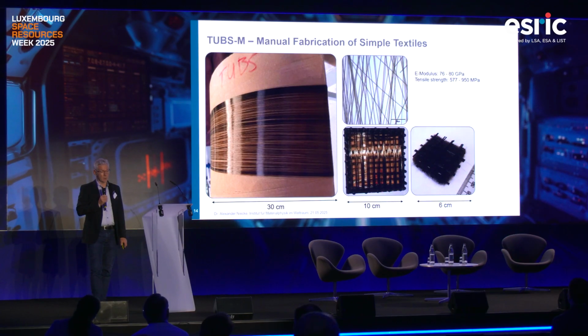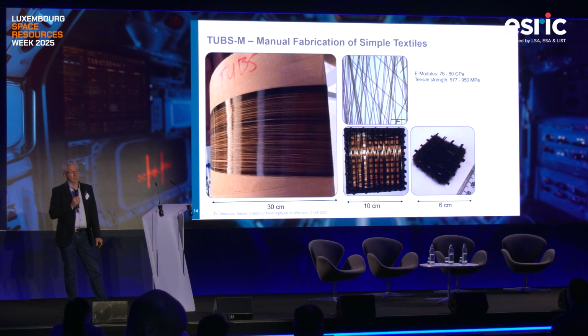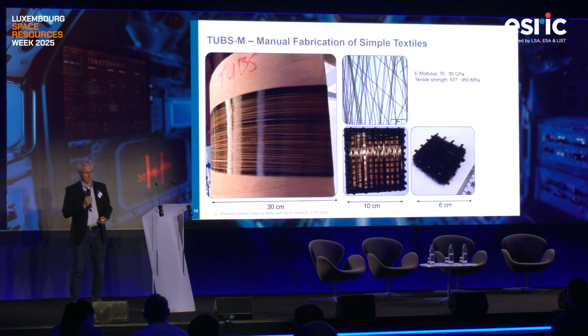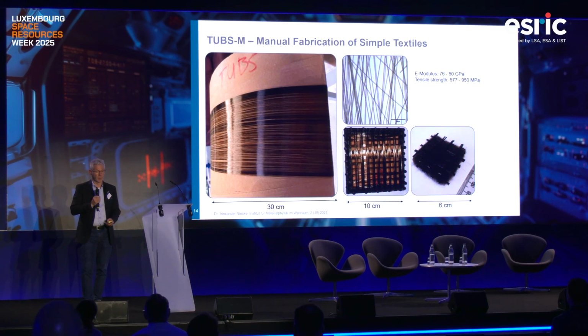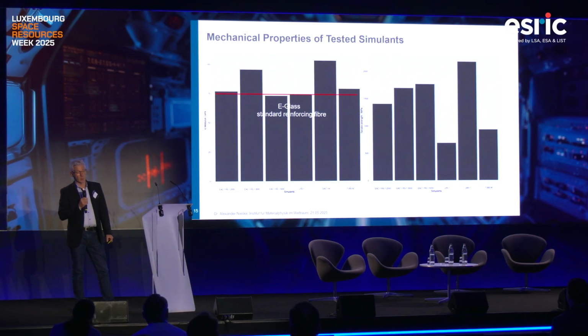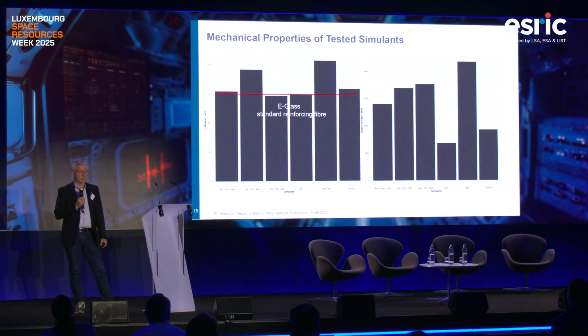TUBS-M is one material that could be fiberized in large quantities, and we were even able to produce simple composite materials and build up some composites for demonstration in a sandwich structure. This is a rough summary of the mechanical properties that we obtained, and LMS1 seems to have the best modulus values, and as reference I added the E-glass standard with 75 gigapascal.